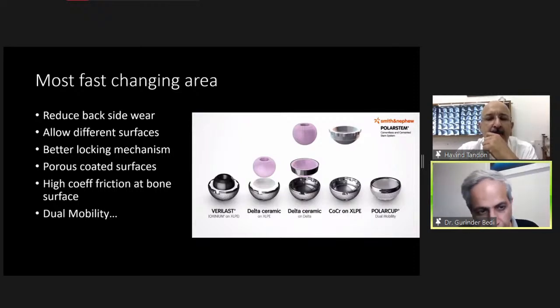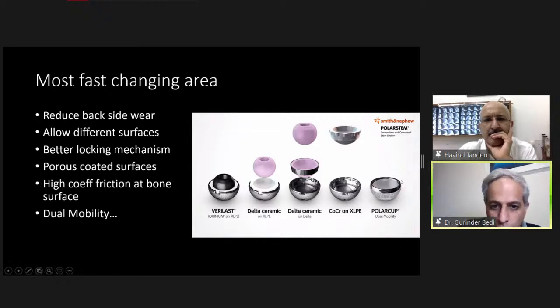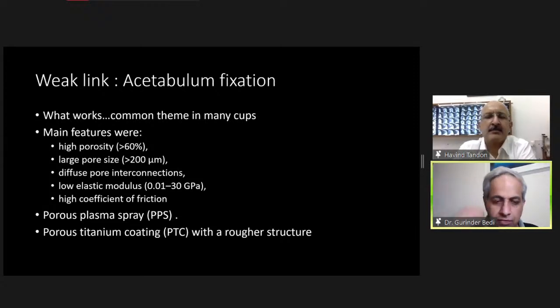What are we talking about in terms of uncemented implants? Things that are changing: we're looking at reducing the backside wear, which is happening between the liner and the cup. We want to allow different surfaces. So every uncemented cup now looks at getting a plastic liner, a different type of plastic liner, or a ceramic liner. Now everybody's talking about allowing a dual mobility liner to also go in. We're all looking at porous coated surfaces and a higher coefficient of friction. So the rougher cups are really, really in. You want one cup which will give you the option of ceramic, plastic, and dual mobility, plus the option of using different heads.